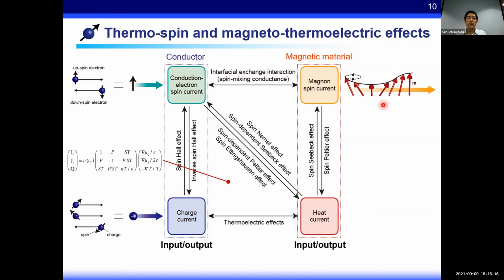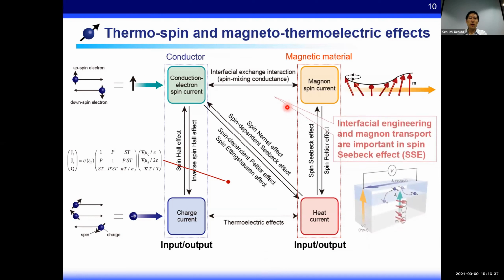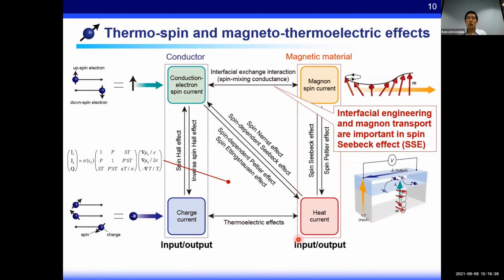The important point here is that basically the inputs and outputs in experiments are heat or charge currents. Therefore, although there are various phenomena, spin caloritronic phenomena result in thermoelectric conversion through various interaction and conversion phenomena. For example, the spin Seebeck effect refers to the conversion from a heat current into a magnon spin current, which is mainly investigated in a junction comprising a magnetic insulator and a paramagnetic metal.